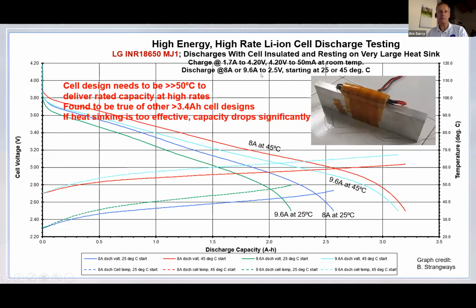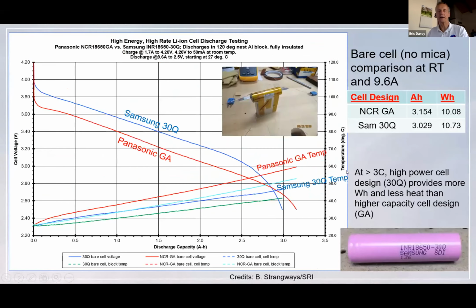In fact, the MJ1 cell from LG in this example here only produces about 2.2 amp hours at the 3C discharge rate of 9.6 amps if you keep it at 25 degrees. So these high energy cells have got to run hot. By running hot, they got to run over 50 degrees in order to deliver a nameplate capacity, and I mean somewhere around 3.2 amp hours. So this pointed us to, we need to go to higher power cells, give up some capacity.